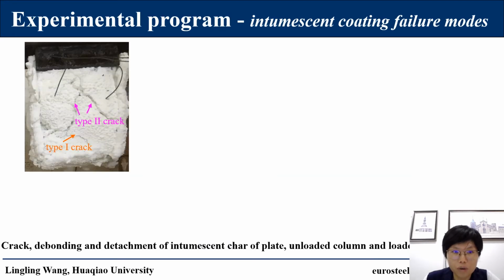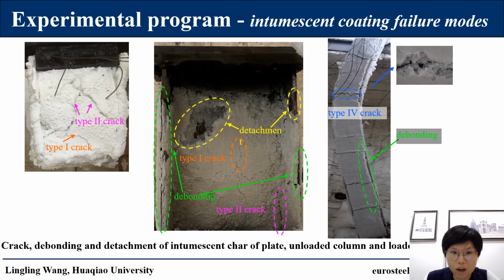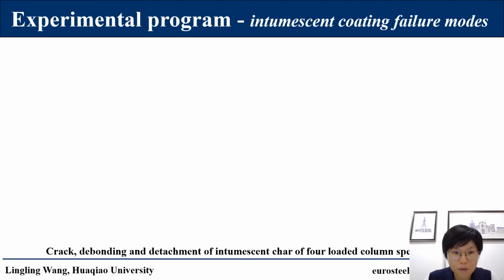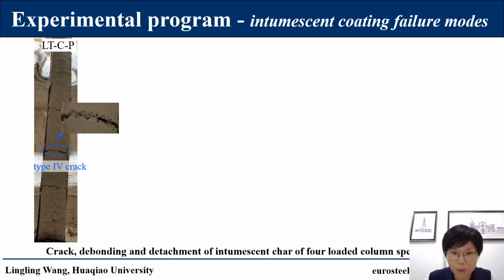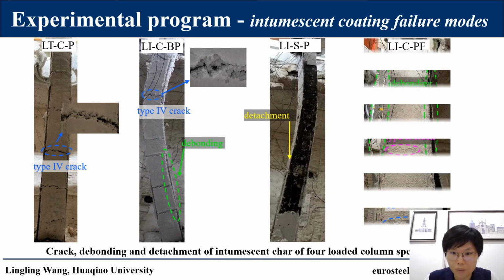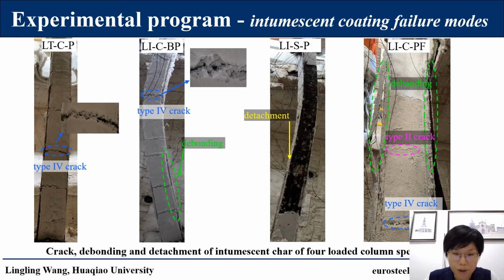These figures show failure of intumescent char for plate specimens and loaded column specimens respectively. Only type 1 and type 2 cracks were observed in unloaded specimens. For loaded column specimens, more serious failure occurred. These figures compare failure of intumescent char for loaded column specimens. Individual treatment has effects on failure modes of intumescent char.